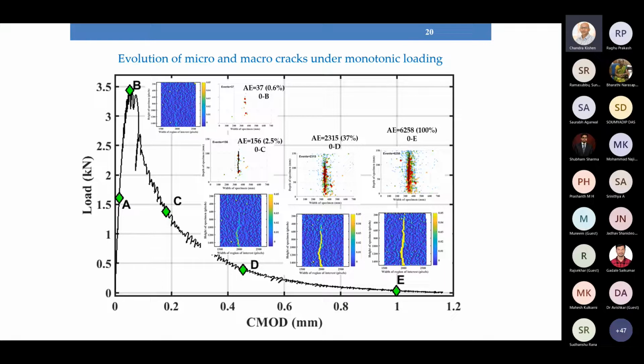What it means is, the micro cracks which occur inside the specimen, when they coalesce, when they join and become a larger crack, the energy content in them will be much higher. As these larger cracks develop into much larger cracks or a major crack, we have a high energy which is dissipated or released, and those are captured by these red large size markers here. Now with this understanding, let us look at the behavior.